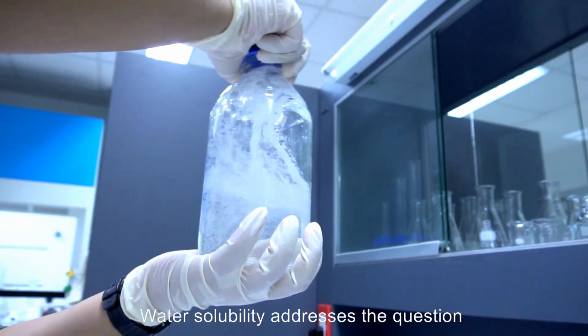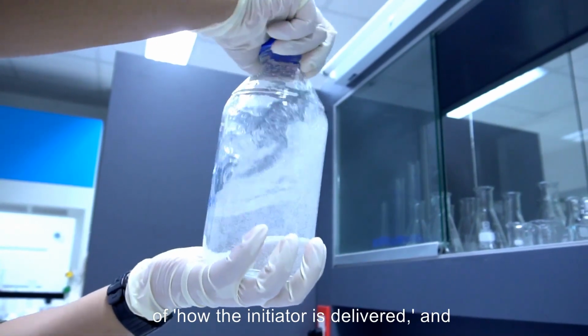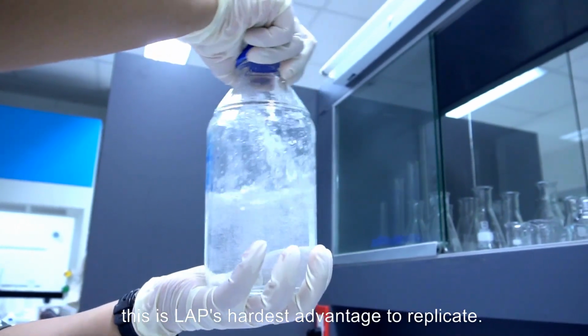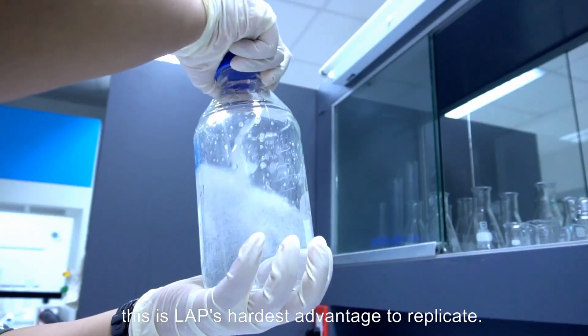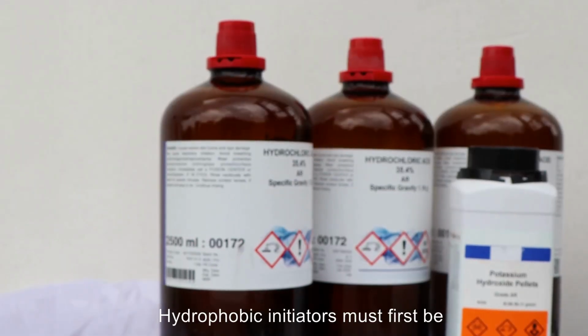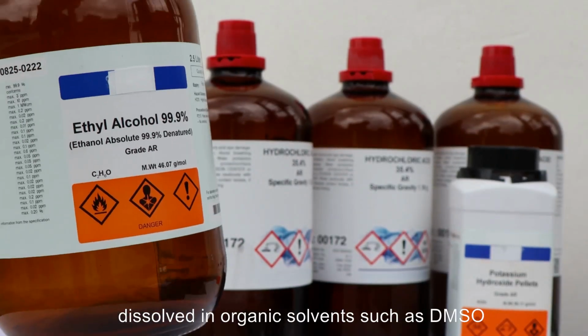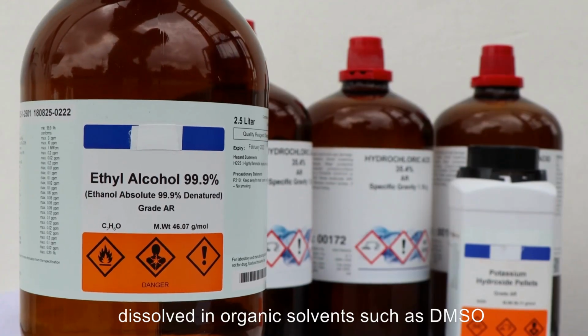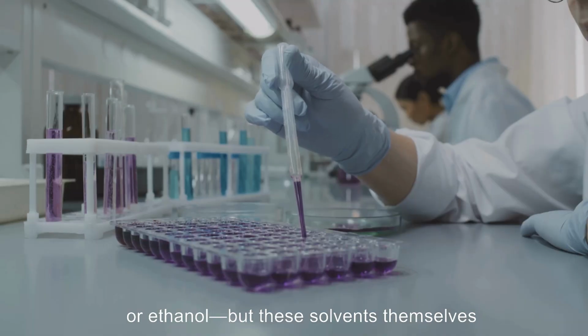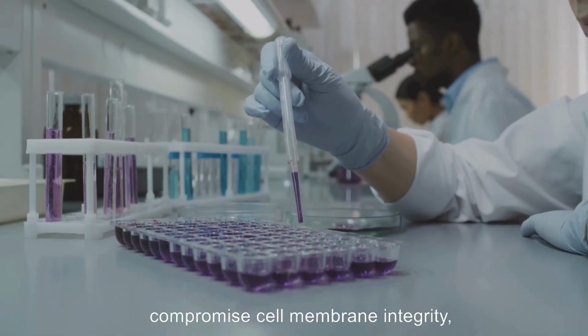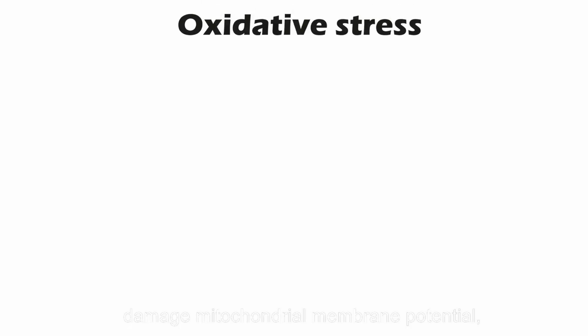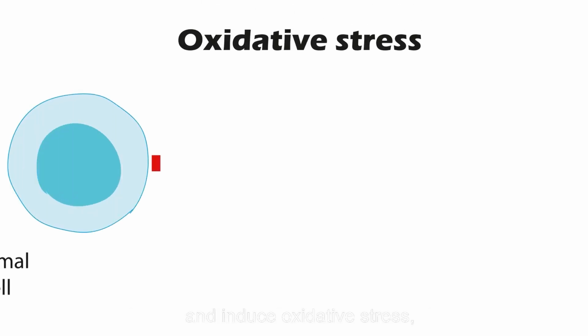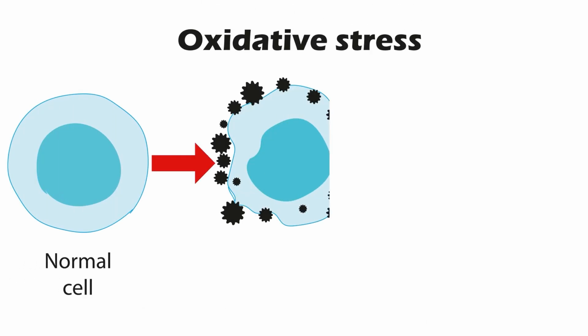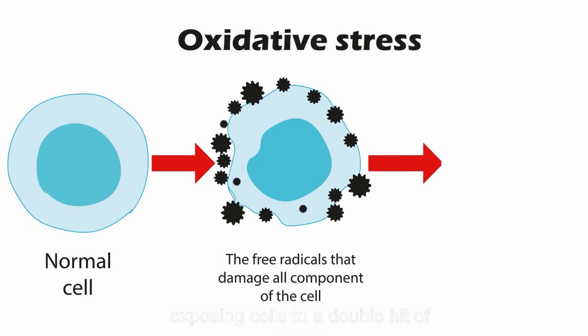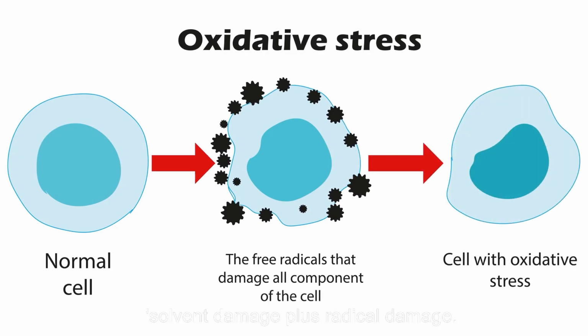Water solubility addresses the question of how the initiator is delivered, and this is LAP's hardest advantage to replicate. Hydrophobic initiators must first be dissolved in organic solvents such as DMSO or ethanol, but these solvents themselves compromise cell membrane integrity, damage mitochondrial membrane potential, and induce oxidative stress, exposing cells to a double hit of solvent damage plus radical damage.